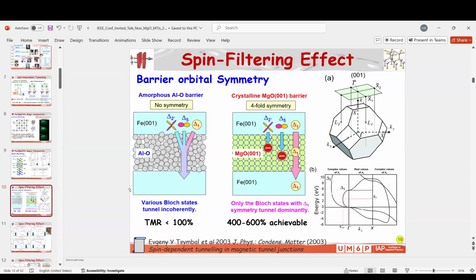Sorry to summarize this, just for people who are not familiar with this. So I will go through this fast. In terms of alumina, aluminum oxide, all the orbitals tunnel in equally, and the barrier itself is amorphous, polycrystalline, right? In opposite, we have a single crystalline MgO, for example. The delta 1 is beneficial, it's dominant, especially in the parallel.